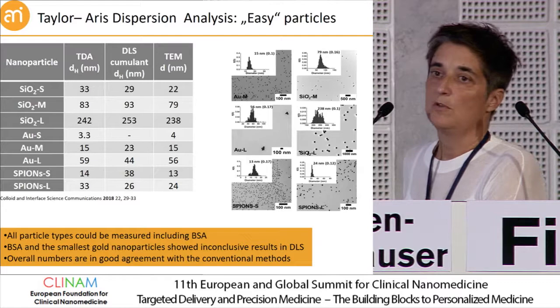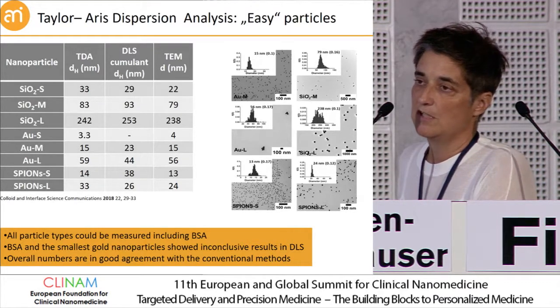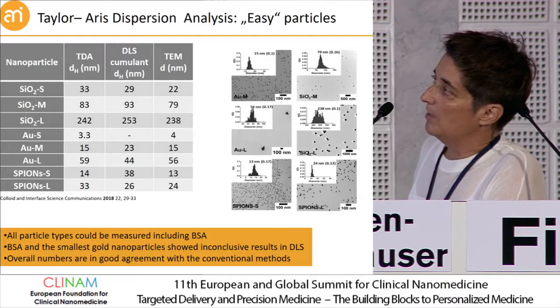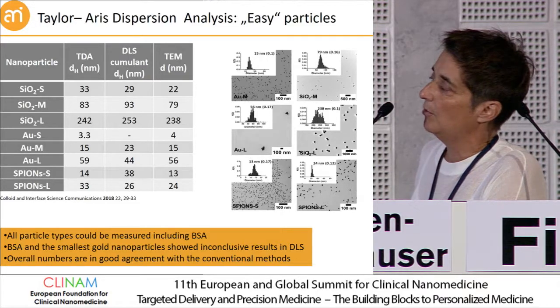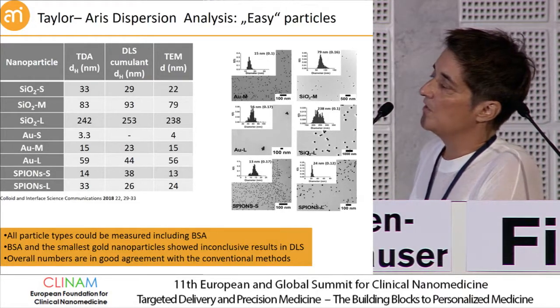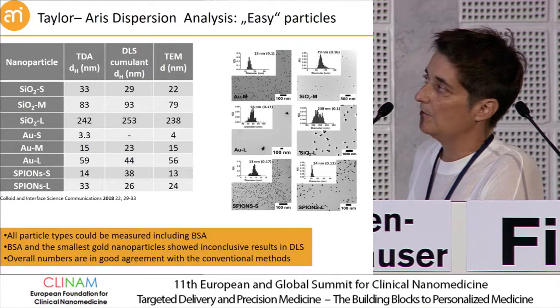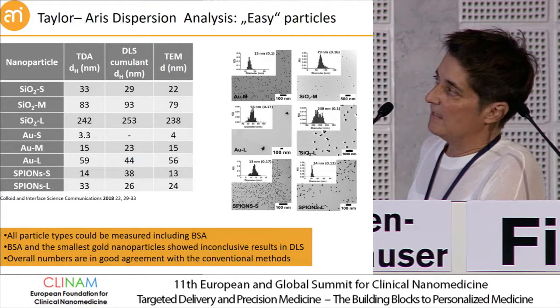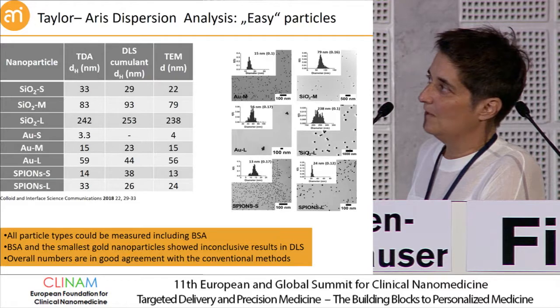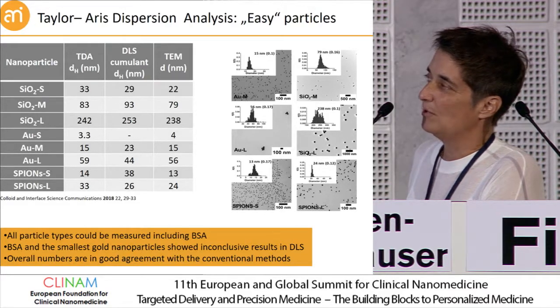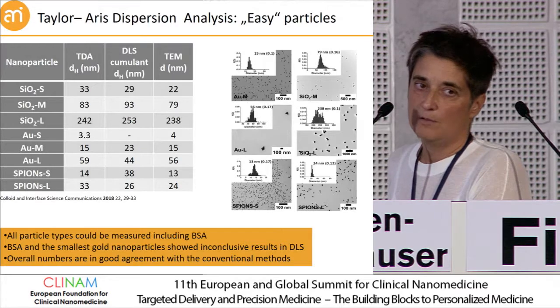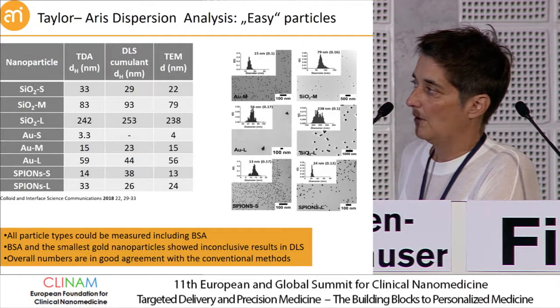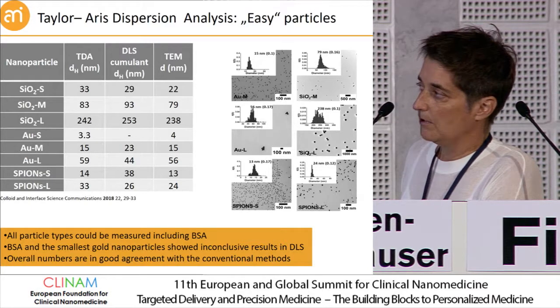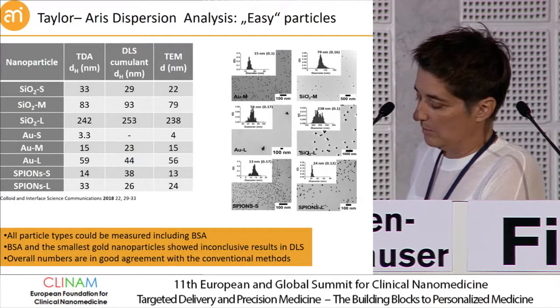As always, we start with model particles, which are monodisperse in size and in shape. So the usual suspects: silica, small, medium, large; gold, small, medium, large; and these are the magnetic particles. Here are some TEM micrographs, and more or less this is nicely comparable for most of the cases with the light scattering data. As an advantage over DLS, with Taylor dispersion analysis you can actually access the really small particles as well, something which is very hard to do with light scattering. You can measure individual molecules like albumin, so this seems to work very well.